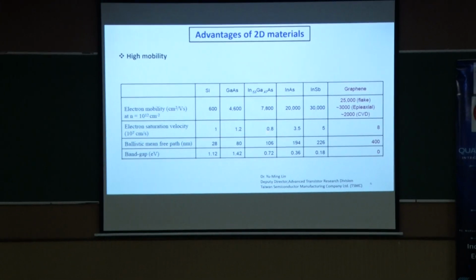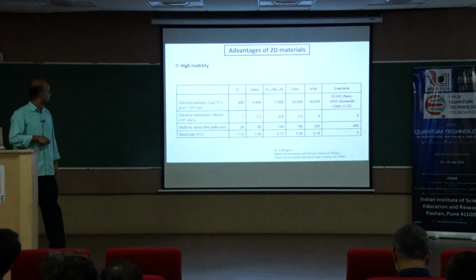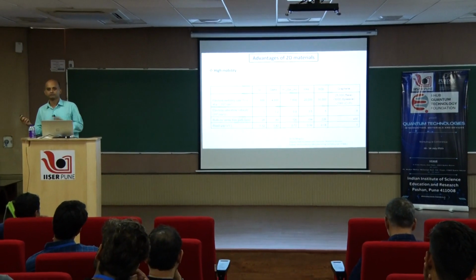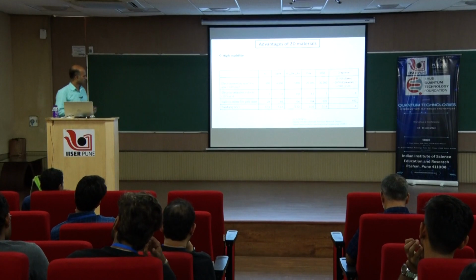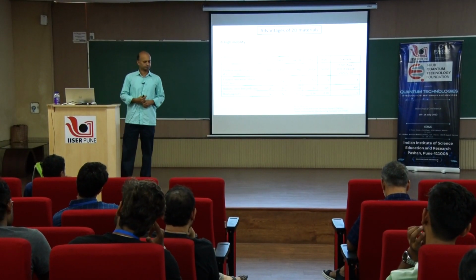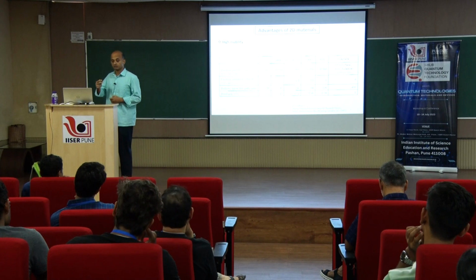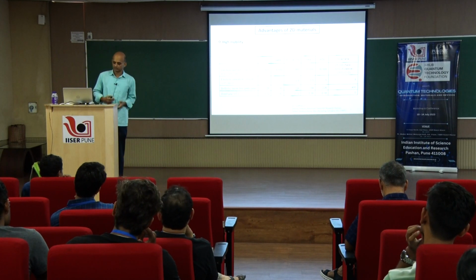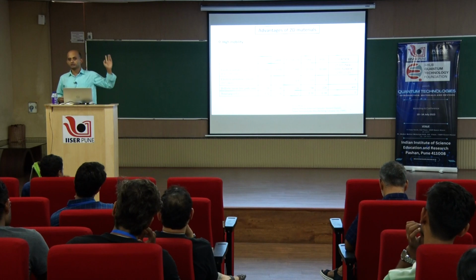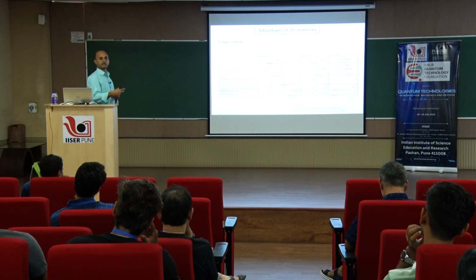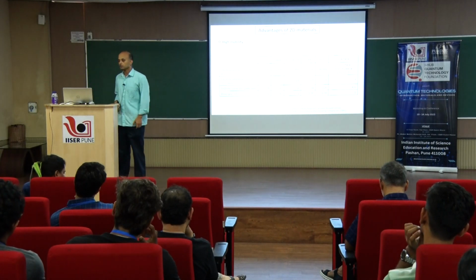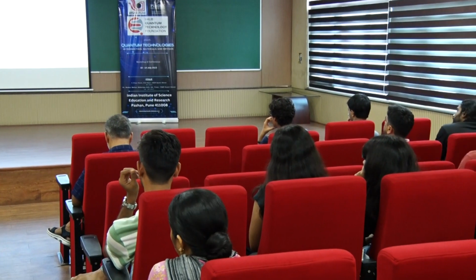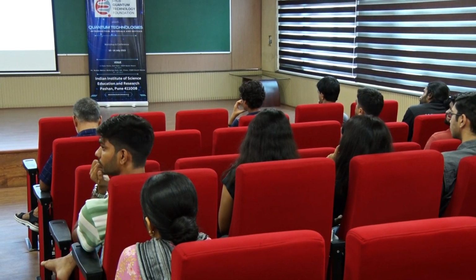Okay, electron saturation velocity. This term, I think if you have read your field effect transistor geometry, says that as you keep increasing the voltage, the velocity of electrons will increase. It's not that it will keep increasing. After a certain time, it will interact more with the lattice and start dissipating. So above that, you cannot really increase the velocity. So your FET characteristics will go like this and then become flat. That flatness comes from the saturation velocity. Saturation velocity is also higher for graphene.